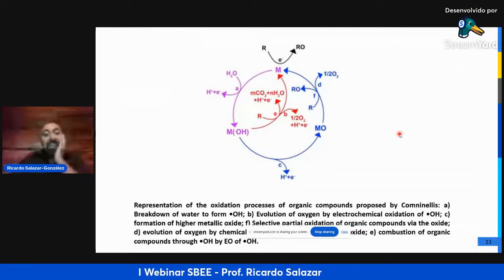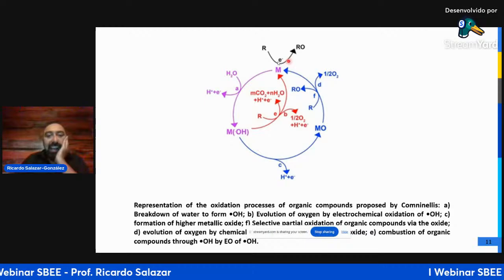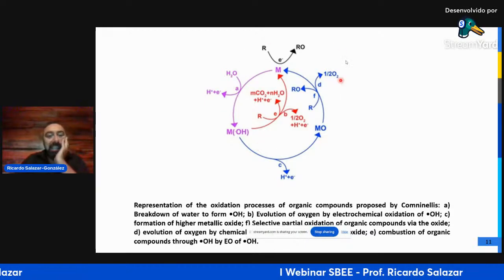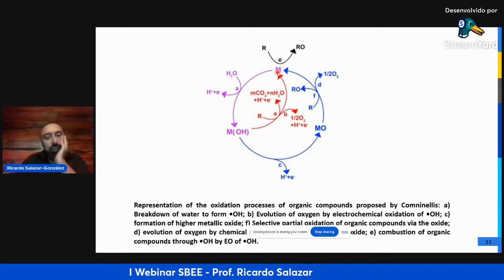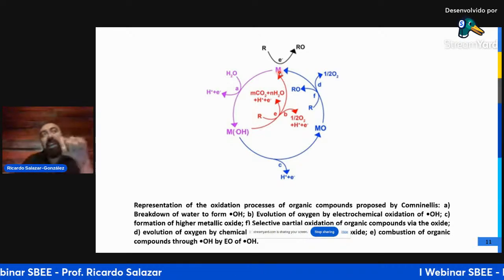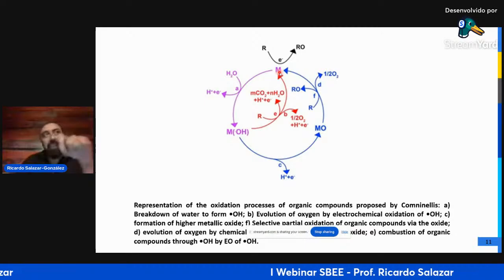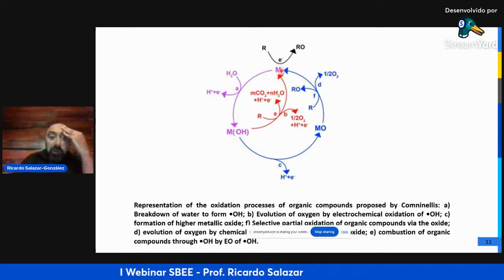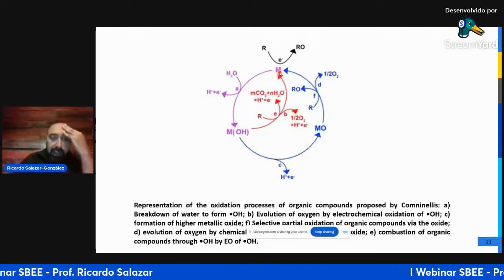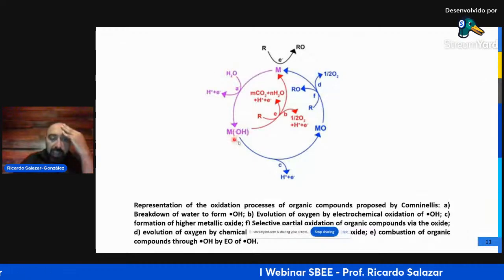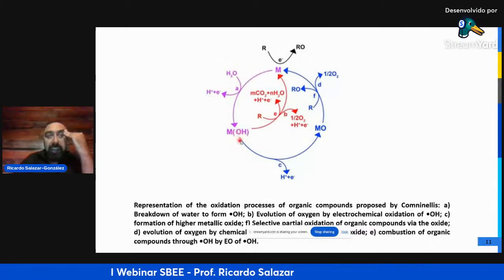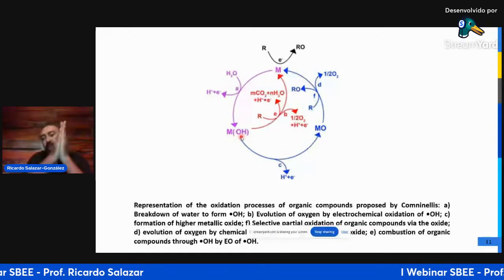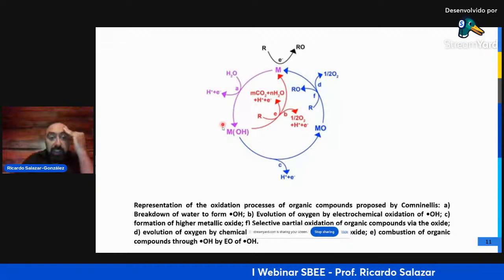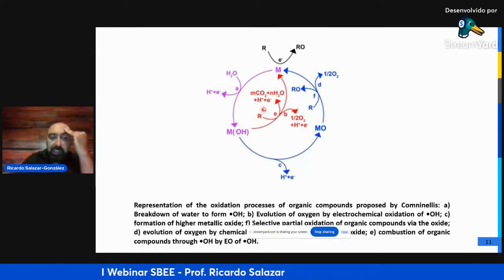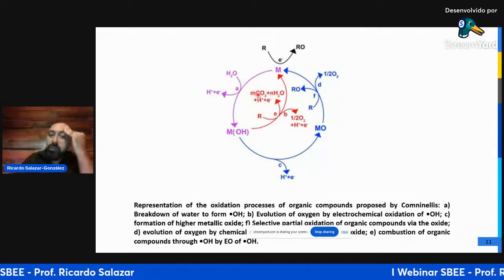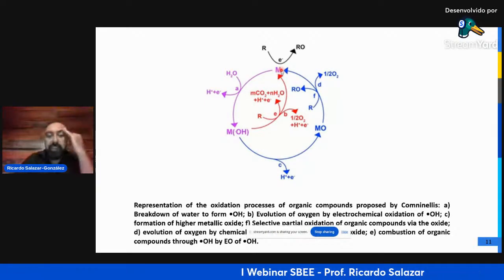Several years ago, Comninellis proposed a classical mechanism to describe the performance of the electrodes during wastewater treatment, specifically for the anodes in anodic oxidation or electrochemical oxidation. The surface of the anodes, where the oxidation of water occurs, produces hydroxyl radicals. These hydroxyl radicals can be physisorbed on the surface, and these physisorbed radicals react with the pollutants in the solution, producing the complete mineralization to carbon dioxide and releasing the surface again.